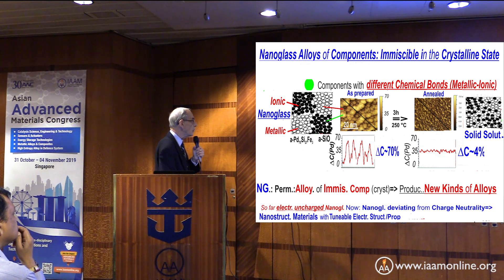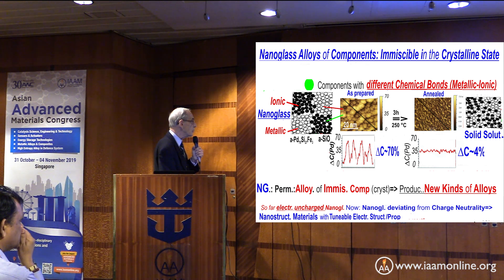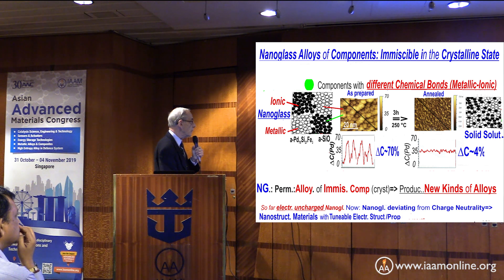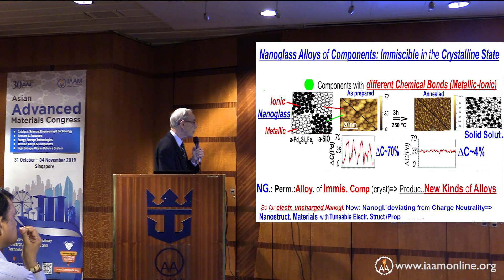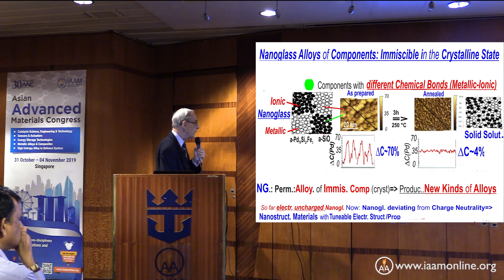When we bring them together, we see what we expect: the individual clusters joined together after consolidation. The chemical composition is also shown here. When we scan across it, we see a very high palladium concentration when hitting a metallic particle, then it goes down to zero when we encounter an oxide particle. This is not surprising.